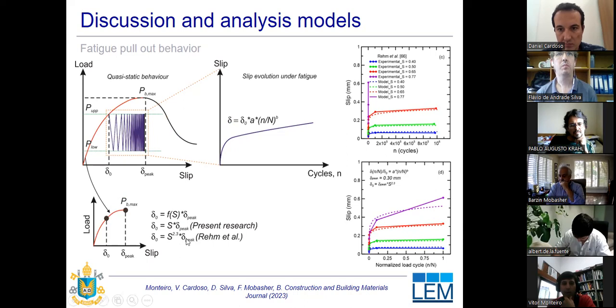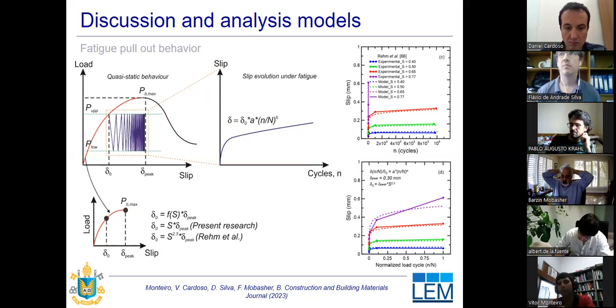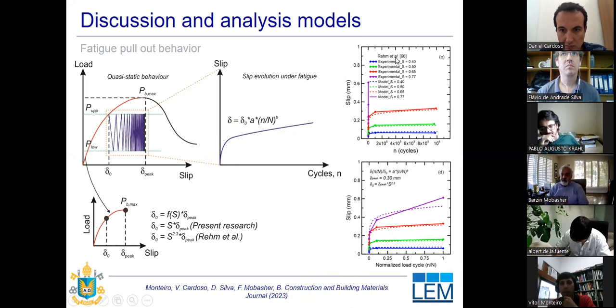But for Rehm et al., we needed to use a different equation. So for each type of parameters that we use in the experimental campaign, we will need to calibrate the initial slip depending on the factors, the rebar diameter, and so on. So it needs to be calibrated in terms of the quasi-static tests that can be evaluated before the fatigue analysis. So we presented good fitting for the different applied load levels. Here we have the results for the other research for the different load levels. So we could verify a good fitting and a good evolution of the slip for all studied load levels from this experimental research.